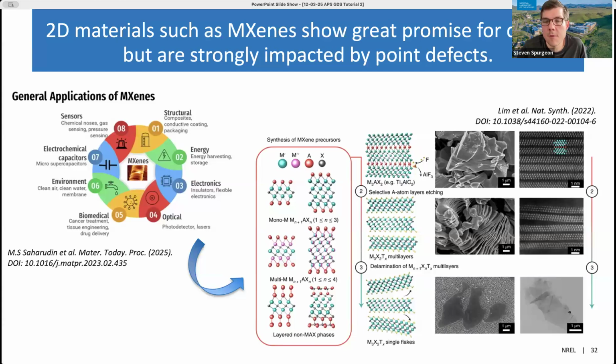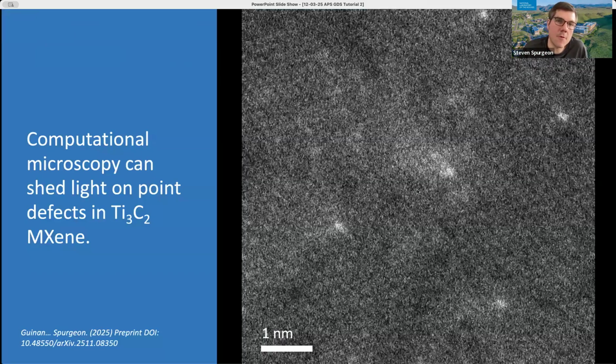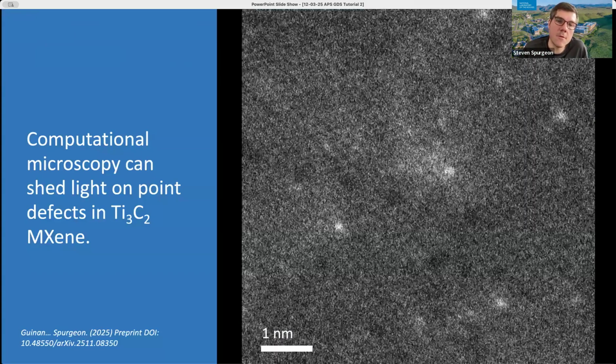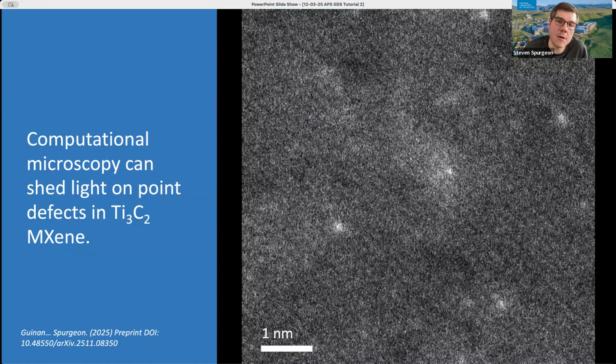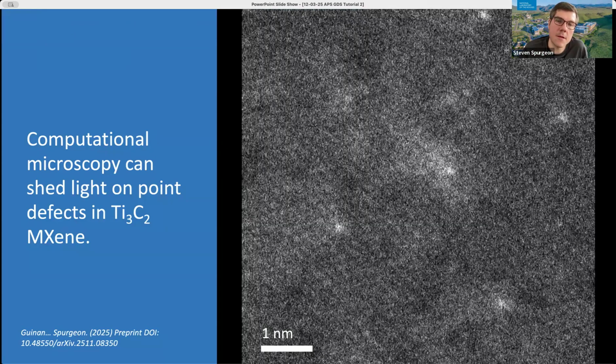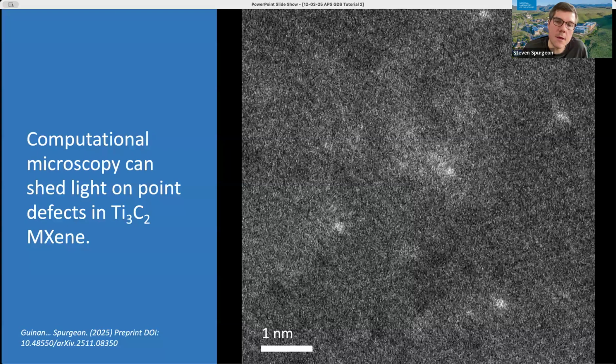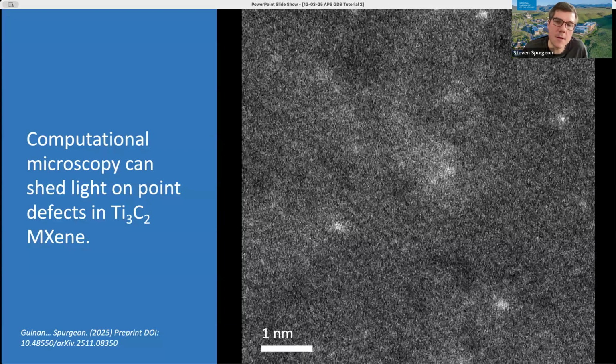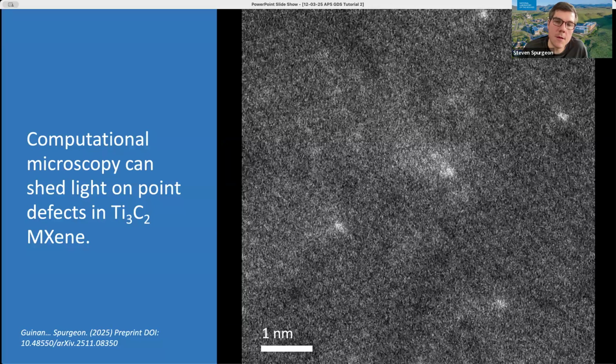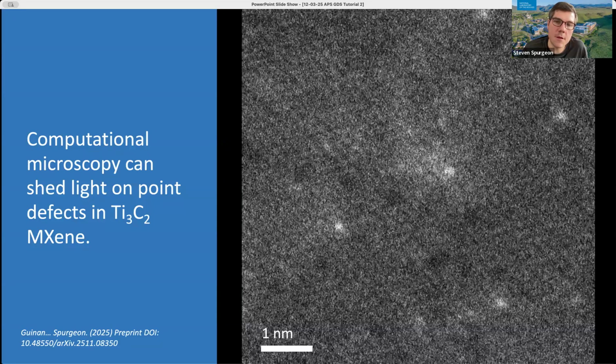The goal here is that when we synthesize these materials, there's a wide variety of different defects that can form. They are, again, either monolayer or a few monolayers in thickness. And so being able to quantify these defects at the atomic level in a way that is scalable and that represents the larger volume of MXene is absolutely critical. So computational microscopy can play a really important role here. What you're seeing on the right is live imaging of an MXene material conducted at 60 kiloelectron volts in our microscope. And the challenge here is signal to noise. We have to be at an incredibly low dose to image these materials, and for a human to interrogate this data is really difficult.